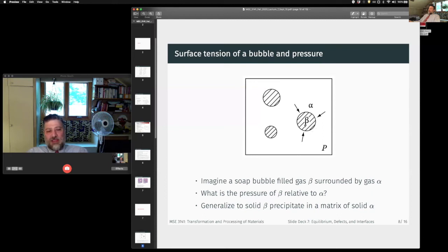So that means the chemical potential inside this small region of beta is elevated. The Gibbs free energy of our phase is going to depend on the nature of the interface between alpha and beta and the size or the volume of this little spherical region.